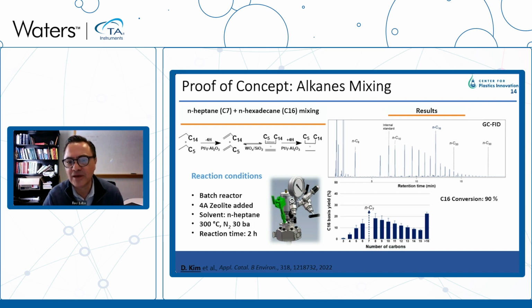And here you can see in the results what happened in this particular graph. You have an internal standard, but as you can see, we start with C7 and C16, and we're forming mostly alkanes. There are small amounts of olefins that you can see at the bottom of this gas chromatograph, but we're succeeding in combining these two types of alkanes. In this particular case, we had to add a new element that was very important, which is the presence of a zeolite. This is the zeolite 4A that you may be familiar with from applications in organic chemistry, which we use as an adsorbent for oxygenates.